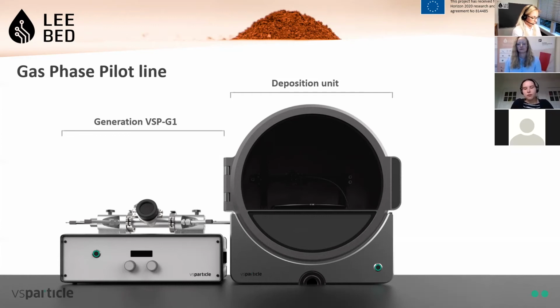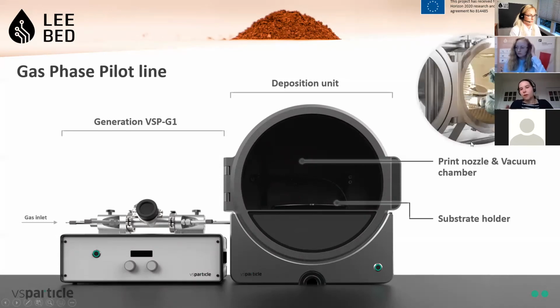So the generation unit generates nanoparticles based on spark ablation and converts bulk material into nanoparticles. And these nanoparticles are transported in the deposition unit, which is equipped with a print nozzle and a substrate holder where you place your substrates. And then the nanoparticles are printed via that printhead onto your substrate. The pilot line uses a pure gas phase process with no solvents added. So the generation of nanoparticles and the deposition are integrated in one continuous process, as I have already mentioned. And first I want to focus on the generation part in the next few slides.